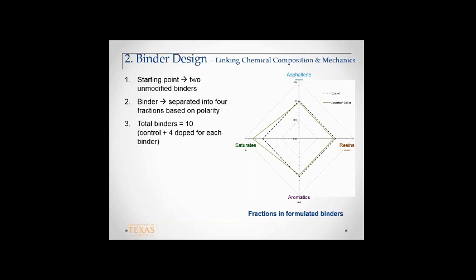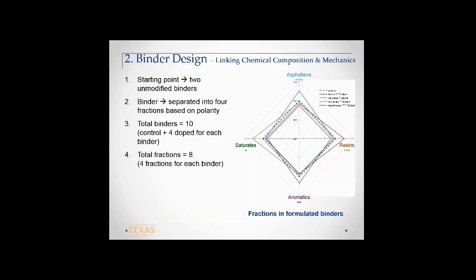And then I do the same thing with asphaltenes, and the same thing with aromatics and resins. So out of each binder, I create four spiked binders, spiked with saturates, aromatics, resins, or asphaltenes. Because I start with one parent and four spiked, that's five, and I have two binders, so 10.